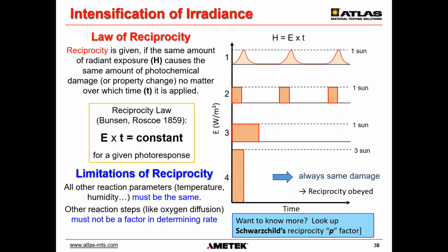Usually the principle of reciprocity is reasonably valid for the photochemical initiation if other parameters like temperature are reasonable. However, the degree of this reasonableness varies, as strict reciprocity obedience is usually the exception. This can result from several factors. While photons initiate photochemical degradation, much of the damage actually results from secondary reactions, usually involving free radicals, and these reactions are mostly driven by temperature and not by photons.